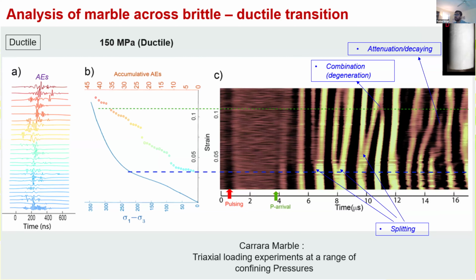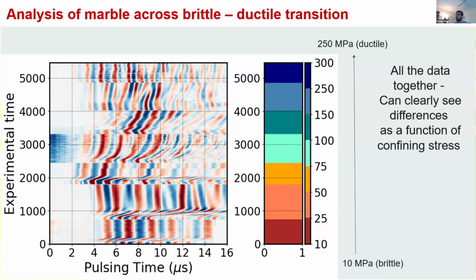Okay. So this is just to show a little bit of what the data looks like. So let's look at all of it together. Rather than looking at two experiments, what does all of the data look like? This is stacking up all of the different experiments' data that we have, all the active source data. At the bottom is the 10 MPa, then there is the 25 MPa, 50 MPa, 75, 100, 150, and then 250 MPa. So we have all these experiments, and this is what the active source data looks like.